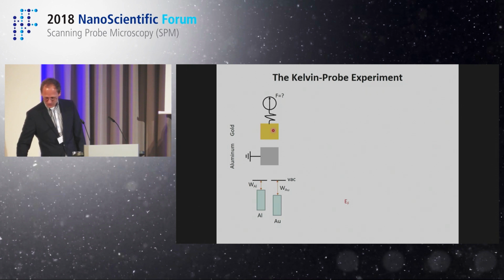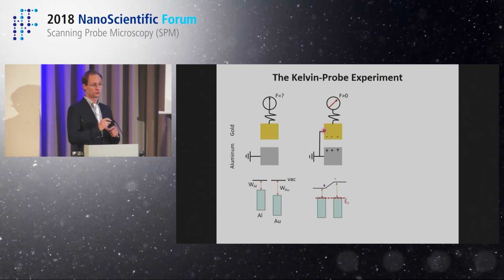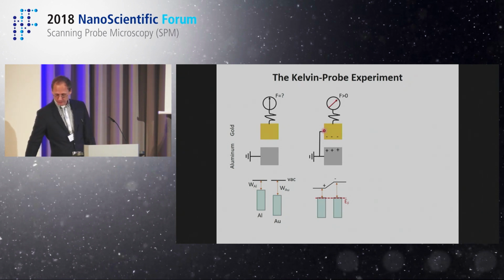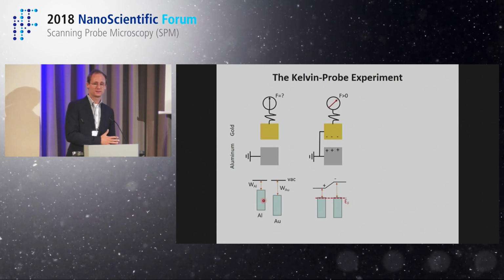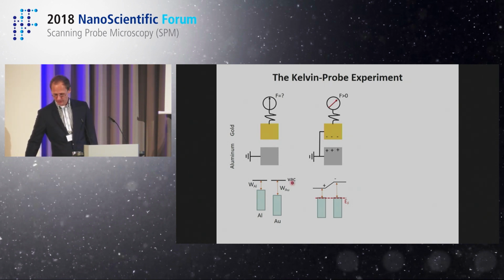So what you would have to do here is, first of all, establish an electrical connection. For example, you could just put the two metal blocks into a short circuit, and then you can see that you have an attractive force. And that's the so-called Kelvin force. This force builds up when we have a look at what actually are metals, and in particular, what is the difference between a noble and a not so noble metal. And this is shown here in the energy diagram.